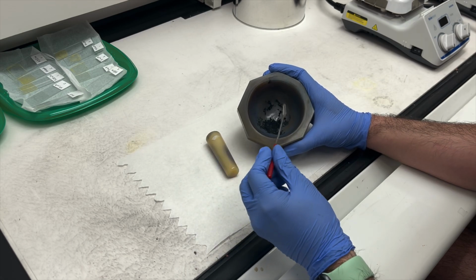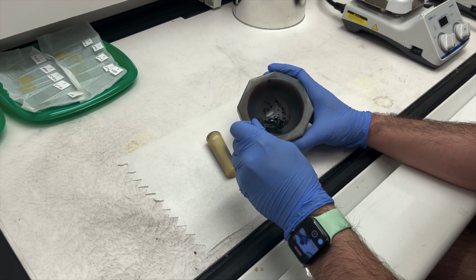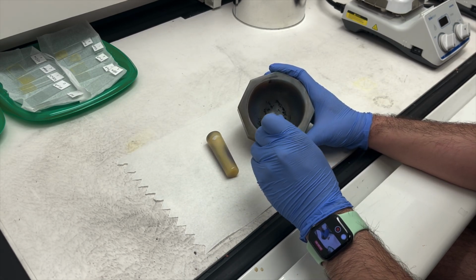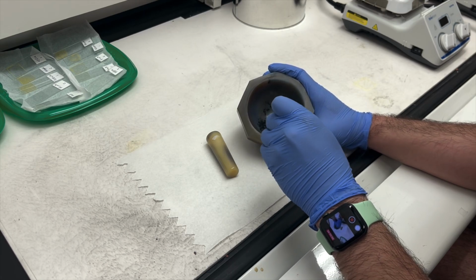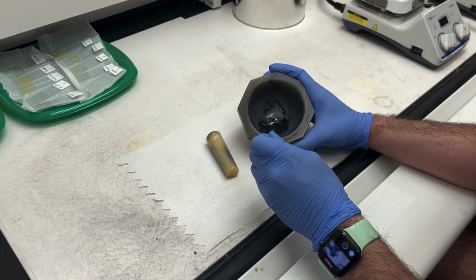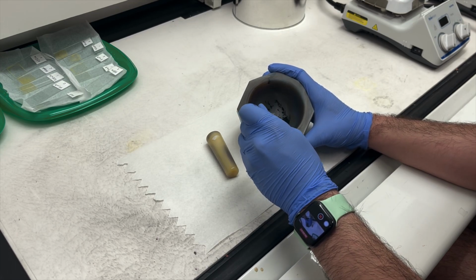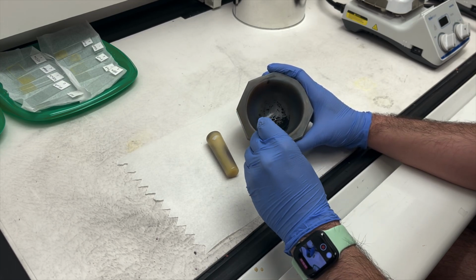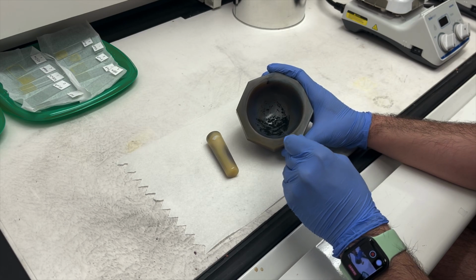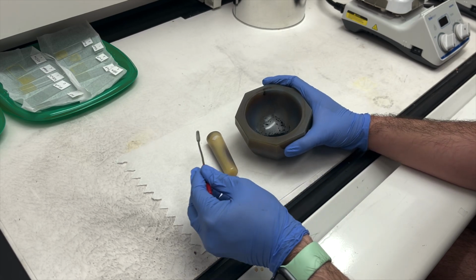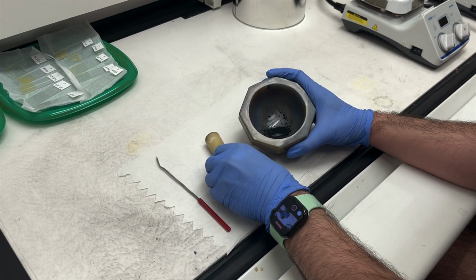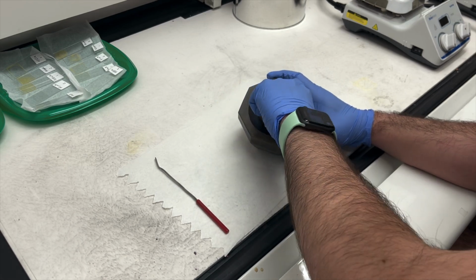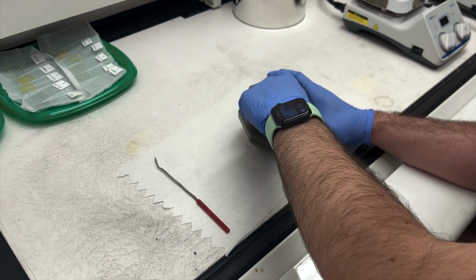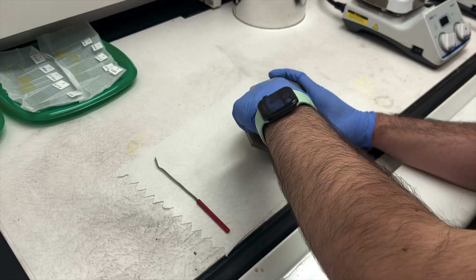So, having started with little circular motions with the pestle, I'm also using the scoop to gather the powders together as much as I can. This grinding will be done for 20 to 30 minutes. And some powders will be lost, so we will try to weigh out our material after grinding to see exactly how much that is. For this reason then, it's better to be a little bit over the target mass than under it for an ideal material ratio.